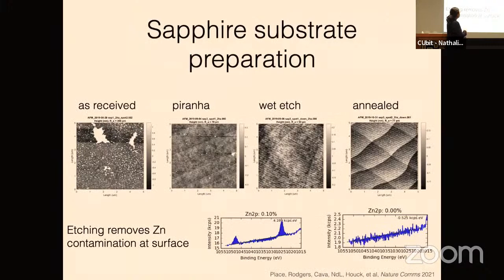The first was just look at your substrates and then try to make them better. And indeed, we could see even just with AFM and X-ray photoelectron spectroscopy that there were a large number of contaminants on the sapphire that we were staring at, the as fabricated devices. And you can do things like clean and prepare the surfaces and anneal them to recover these nice step edges on the sapphire and make sure that you don't have any of these heteroatom contaminants.